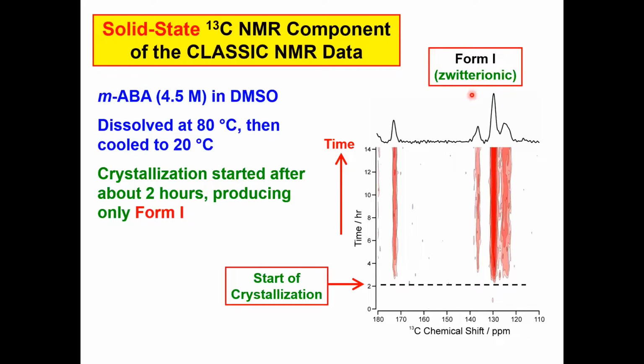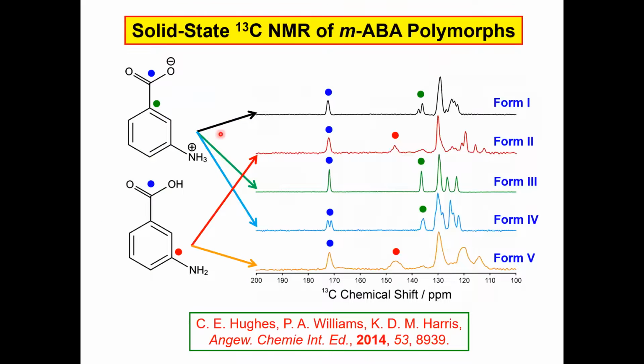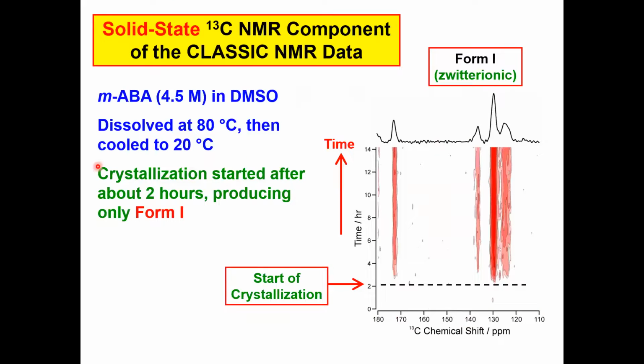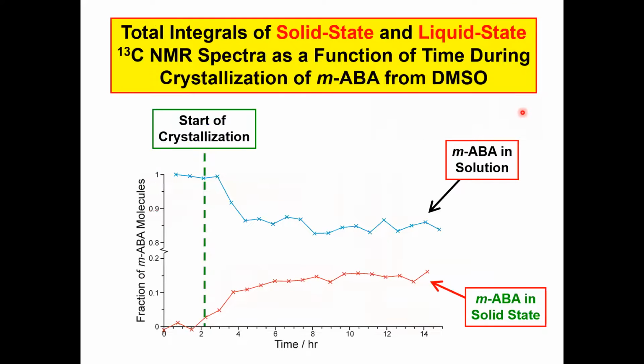And I should emphasize, actually, let's go back to this. Some of the polymorphs are zwitterionic, others are non-zwitterionic, and that's going to be important in a moment. But in this particular experiment, we produce polymorph 1, which is known to be zwitterionic. There's actually no polymorphic evolution in the solid form during the experiment. Looking at the total integrals of the solid state and liquid NMR data, we can see no change in the amount of the solid, no presence of the solid in the first 2 hours. We only have the liquid.